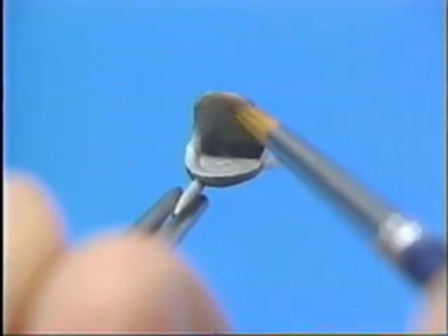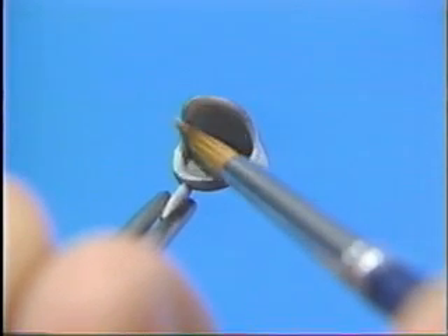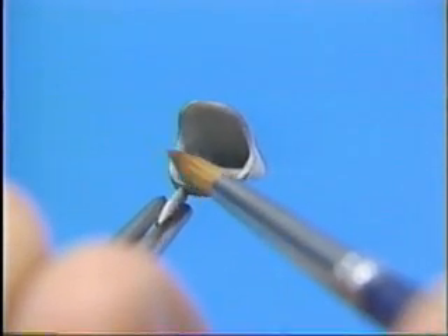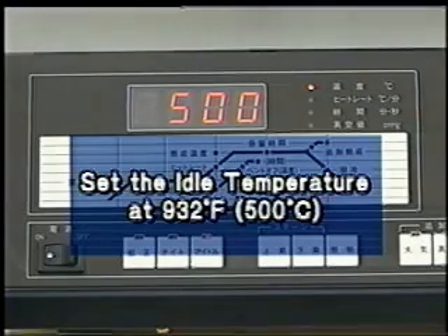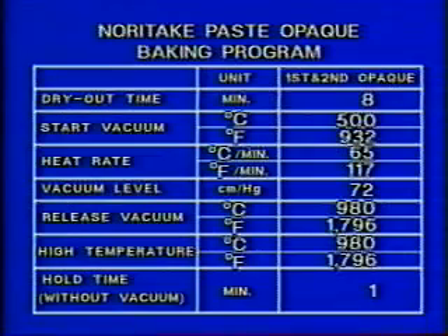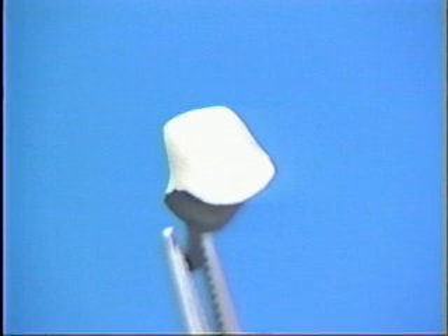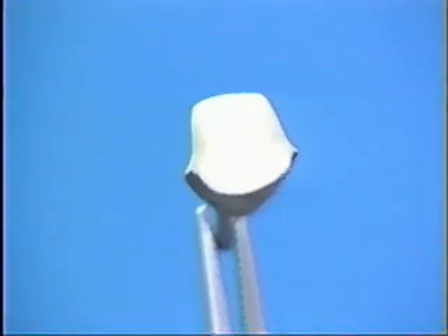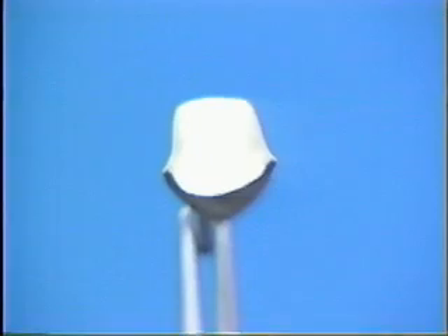Check if there is any contamination of paste opaque on the inner surface of the metal framework. Get rid of the contamination with clean and dry brush. For the baking of paste opaque, set the idle temperature at 932 degrees Fahrenheit. For the first baking, raise the temperature from 932 degrees to 1796 degrees at the speed of 117 degrees per minute. Then hold it at 1796 degrees Fahrenheit for 1 minute at room atmosphere. That finishes the first baking of paste opaque. Suitable baking reflects the slight luster on the porcelain surface.